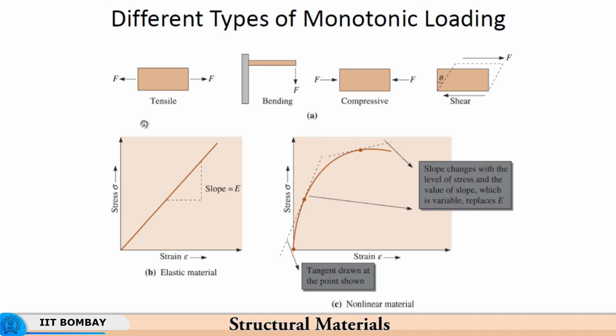Supposing the shaft is of infinite E, then there will be no strain, and then the fatigue life will also be practically infinite. But that is not the case with any practical material. So, you take a practical material, it will always deflect. Deflection may be immeasurably small, but the material will always deflect, and due to that it will result in elastic strains, tension and compression, at the top surface as well as at the bottom surface, and as a result you will find damage accumulating in the shaft. So, this is a very important aspect for structural materials. Deflection has to be only elastic, it is recoverable in nature.